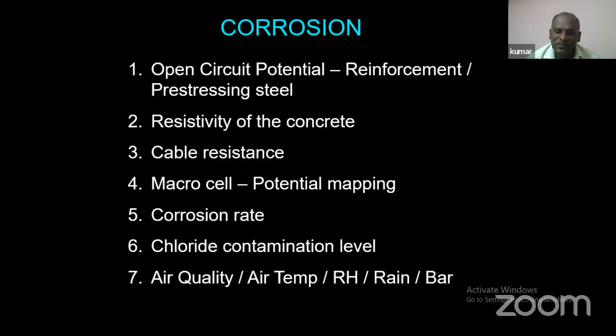And what happens? Reduction of pH is happening, and there is also a volume increase. There will be a deterioration of the concrete. Number one is steel reinforcement corrosion. Second one is deterioration of the concrete. So both together, your structure is going to fail completely.